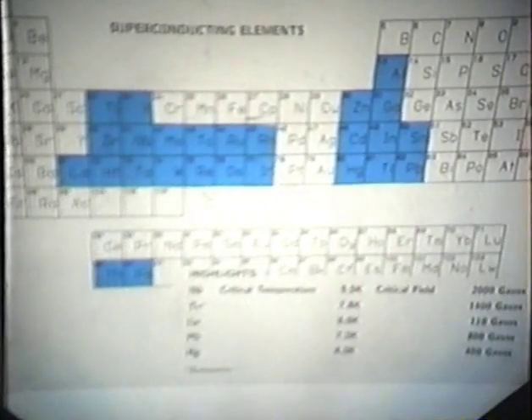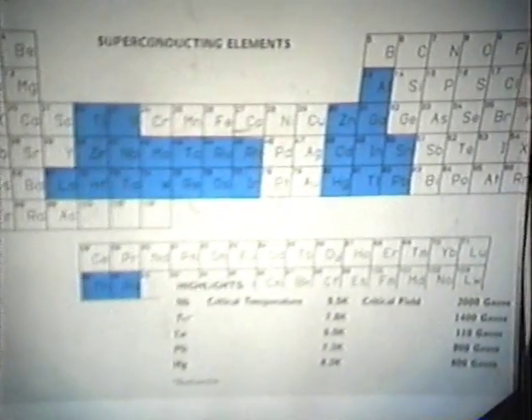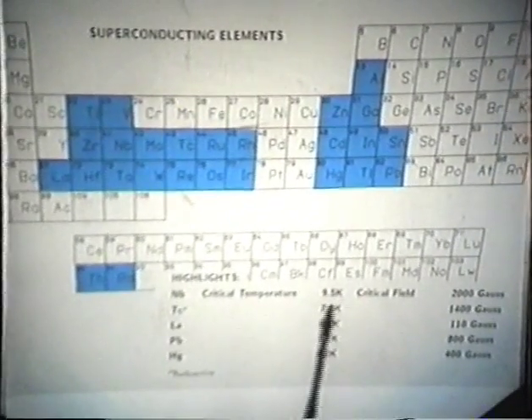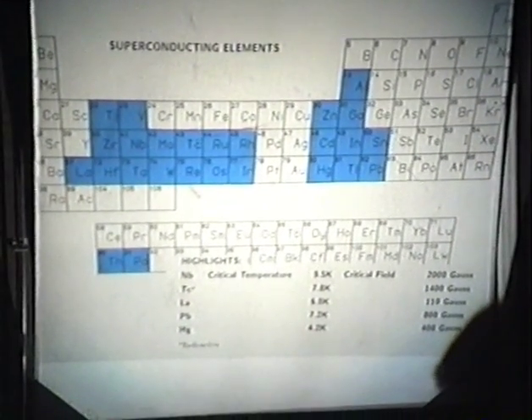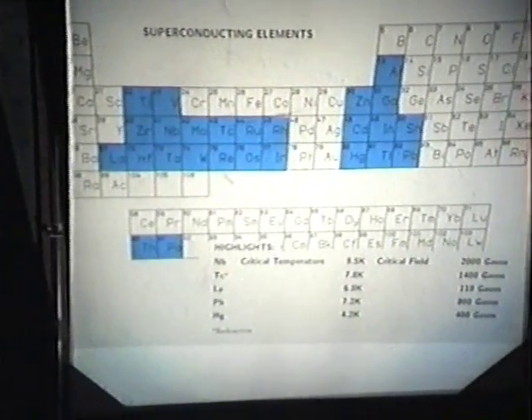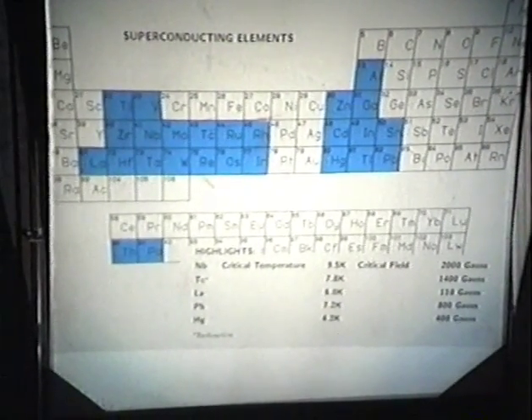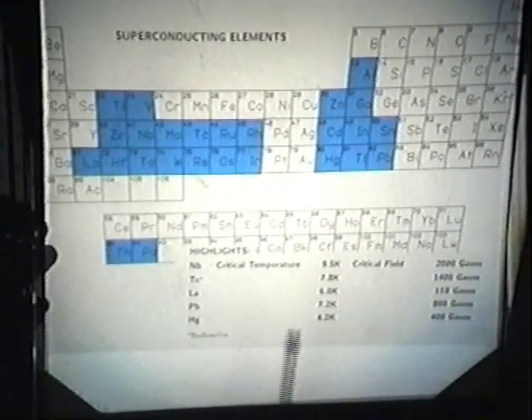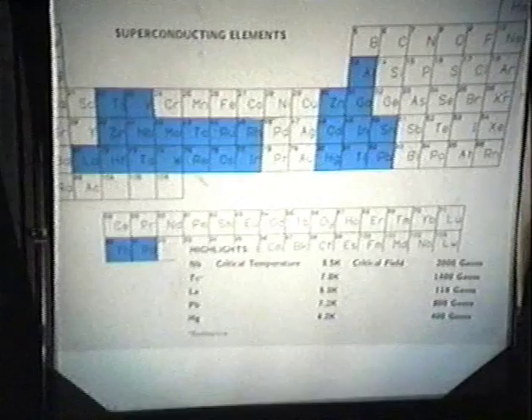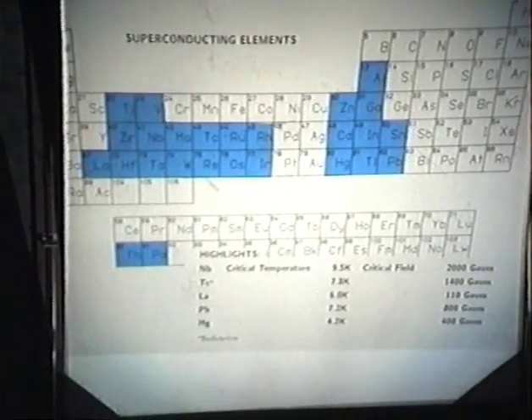And they quickly ran into problems because the superconductors, the ones that were discovered 30, 40, 50 years ago, even 70 years ago, all suffered from a limitation in that as you raise the magnetic field by increasing the current around the superconductor, either by passing a current through the superconductor itself or by some other method, you quickly found that you destroyed the superconductivity. It went away. And in fact, for mercury, as little as 400 Gauss was sufficient to destroy the superconductivity.